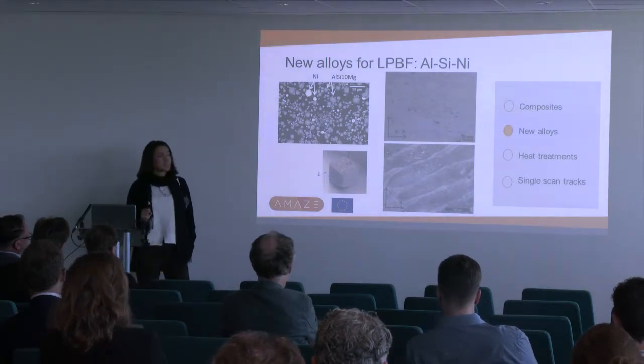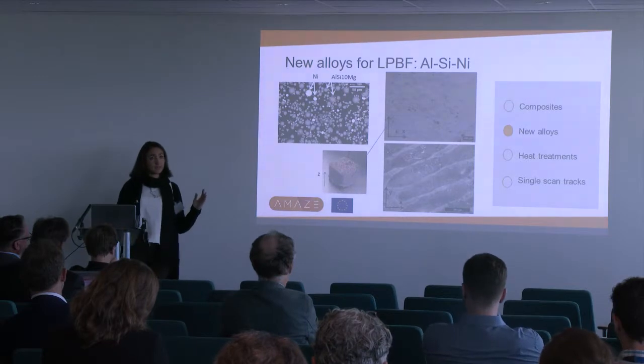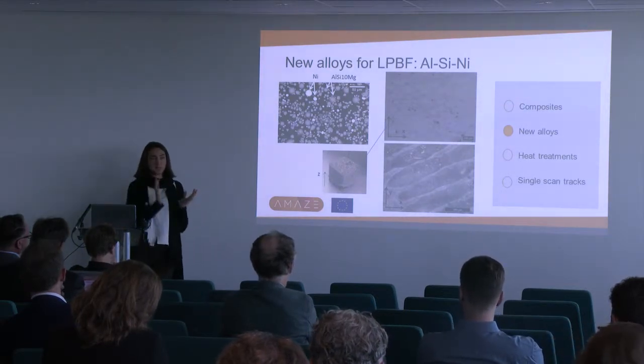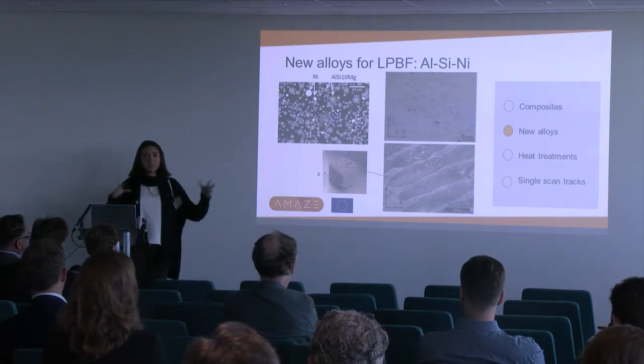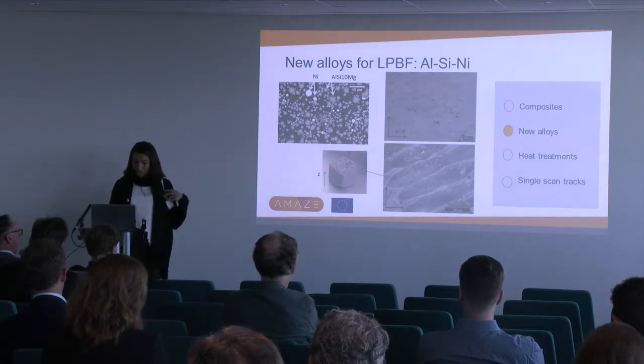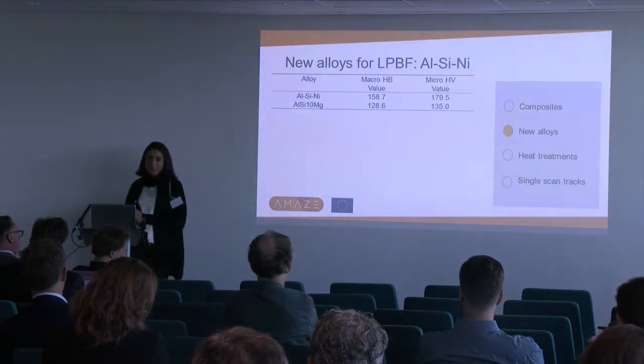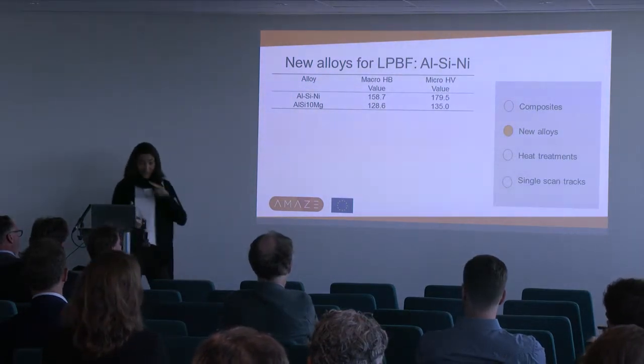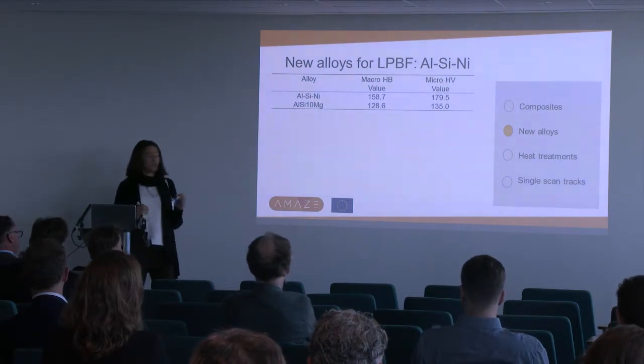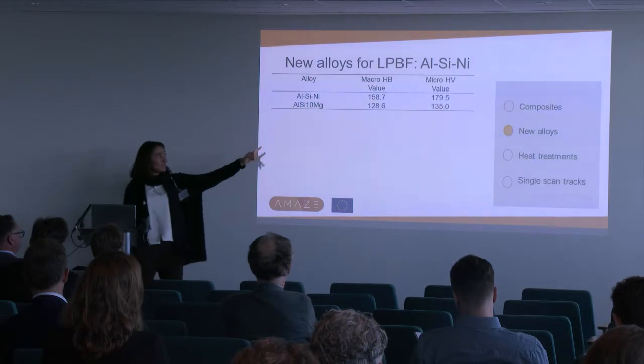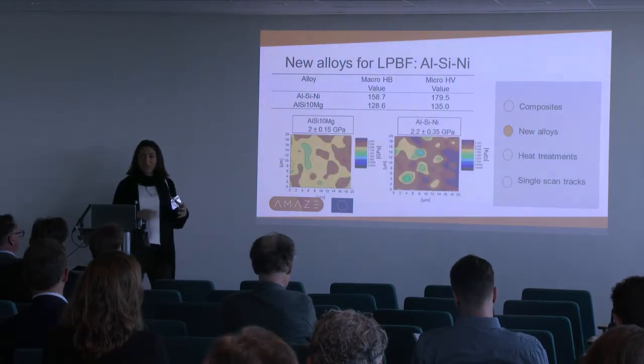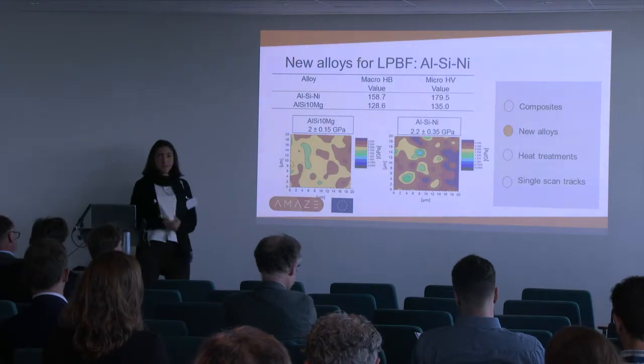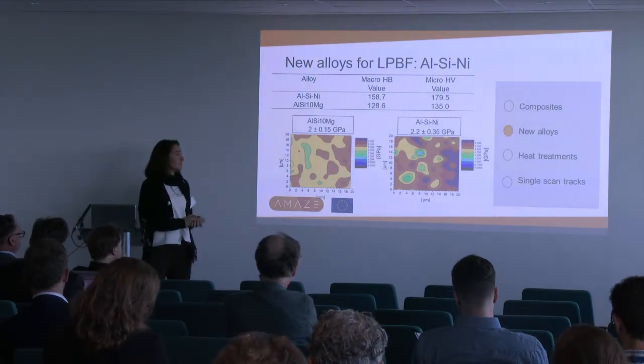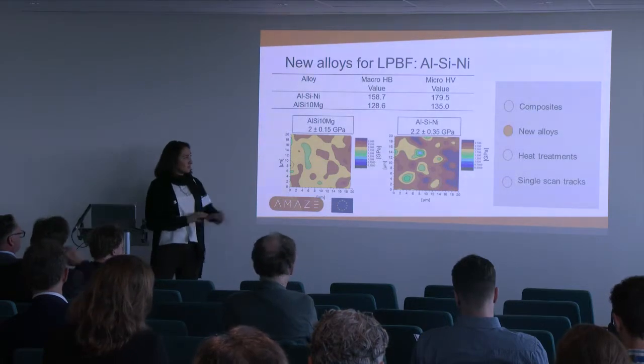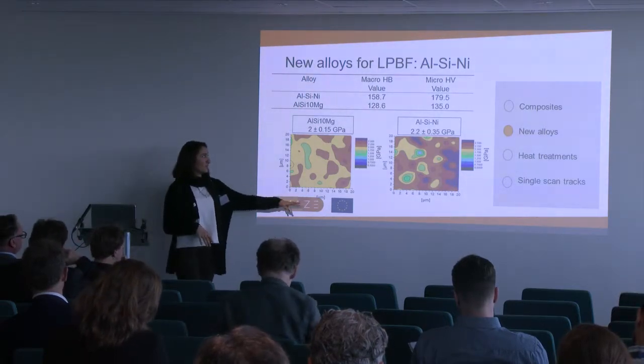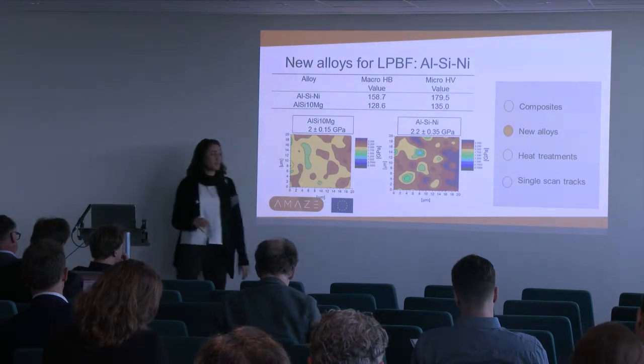So it was promising. We have the microstructure along the building direction, so we can see the usual microstructure made of melt pools. And on the top, we can see the shape of the melt pool as well. Then we went to see the mechanical properties. So we checked the hardness. We compared it with the hardness of the aluminum silicon 10 in a macro scale, a micro scale, and a nano scale. So in any case, we could achieve higher hardness. So this alloy composition seemed suitable. So here we have the nano hardness of the aluminum silicon 10, and this one is the aluminum silicon nickel.